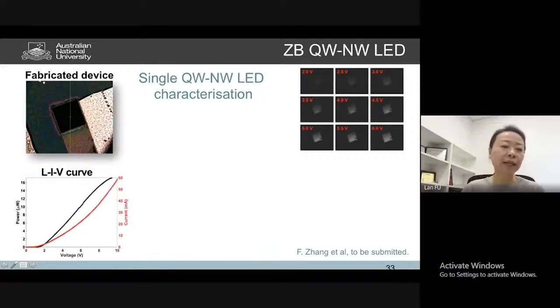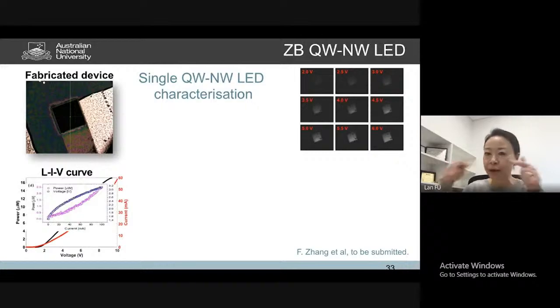And if you look at the LI curve, in particular, pay attention to the power. So this is a 16. For this particular device, we can turn on at 2 volts, and we have a large 16 microwatts coming from our nanowire array. This compared to the previous triangular faceted nanowire, which we could only achieve about, what is that value? Yes, about 3-4 microwatts from there. We have a much larger enhancement of the power from our modified hexagonal-based nanowire.